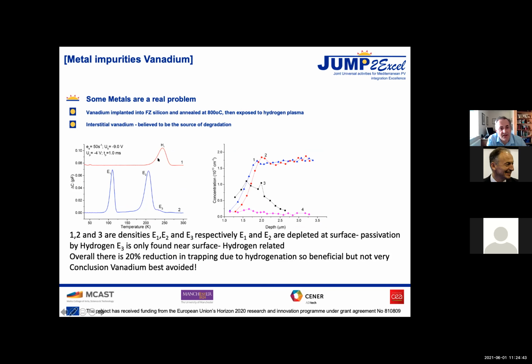And then when we did that, we found in DLTS, again, these correspond to traps that are emitting electrons back into the conduction band, and we can see a series of peaks. And these are like fingerprints. We know that these correspond to particular energy levels. They're vanadium related.